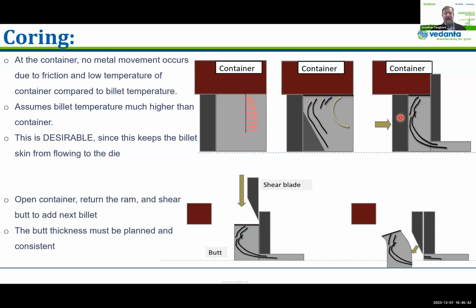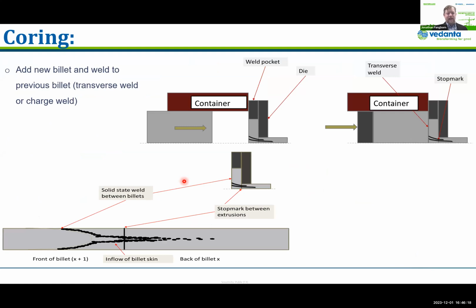However, in order to actually get all of it, even with very good billet quality, very state-of-the-art, we would have to take like 4 inches, 10 centimeters, and then we have other problems. For example, the blisters we just talked about. So in practice, we have the shear coming down, taking the butt off, and most of this billet skin, but we're likely to have some of it in the die or in the profile on the next step. And then when we add a new billet, of course, anything that's in the die is going to push out. Remember, anything that goes into the process has to come out.